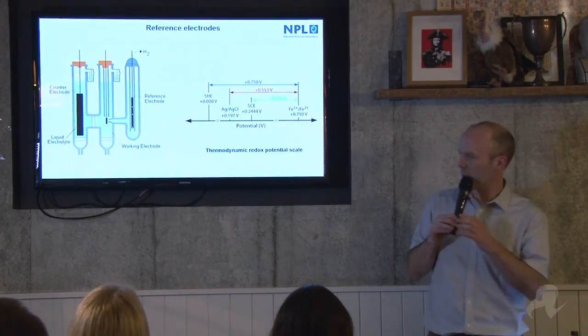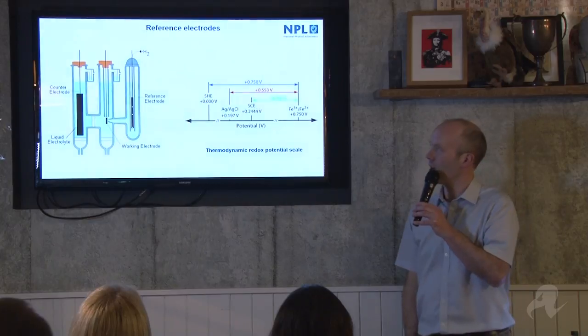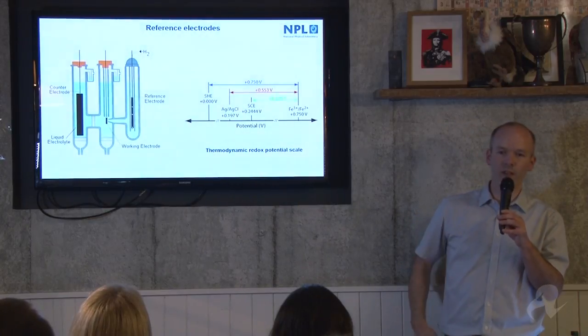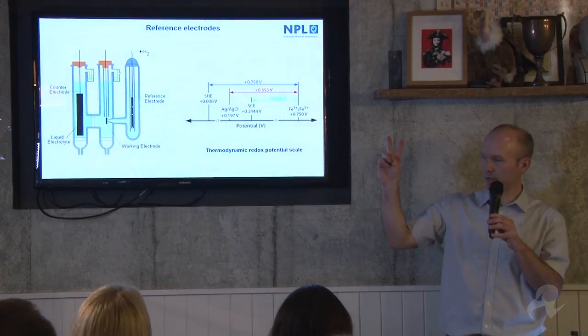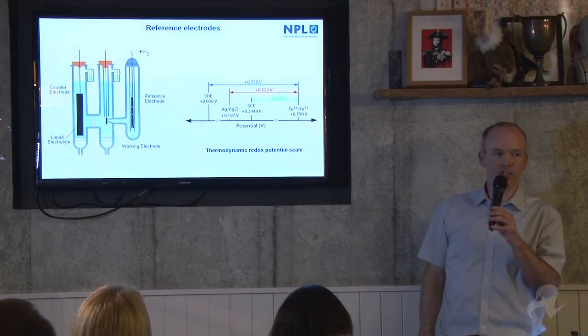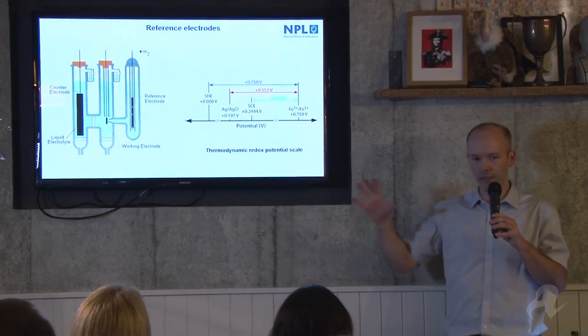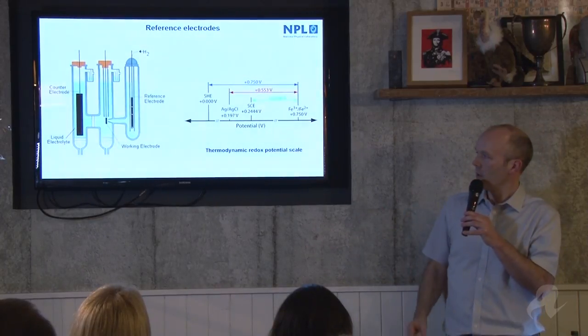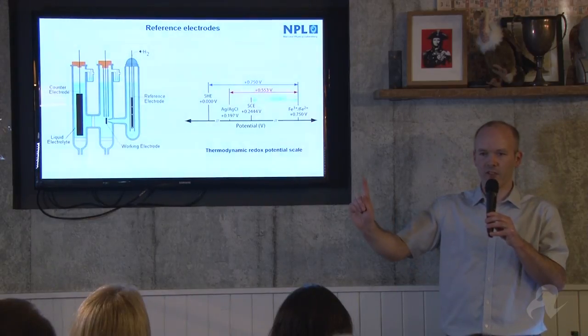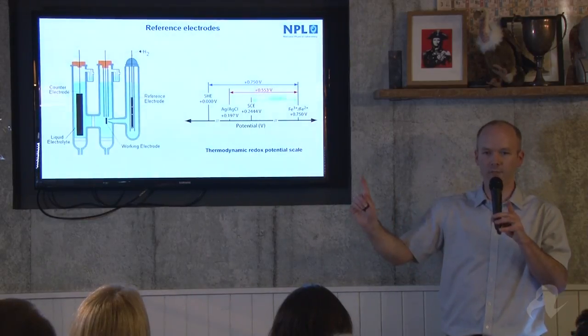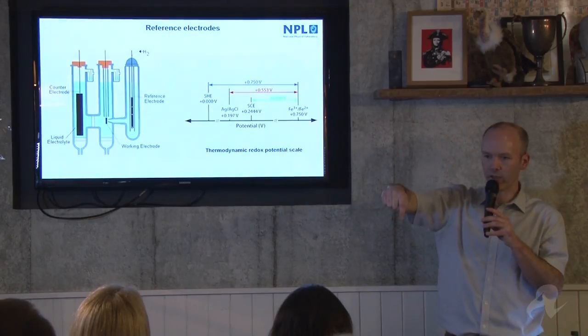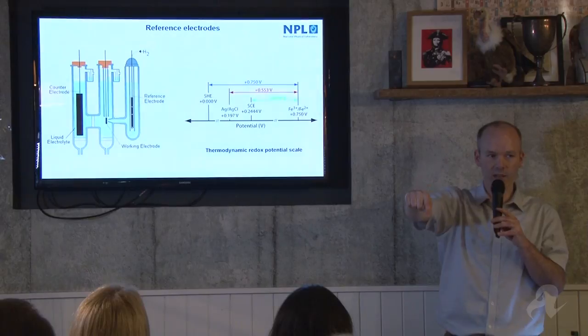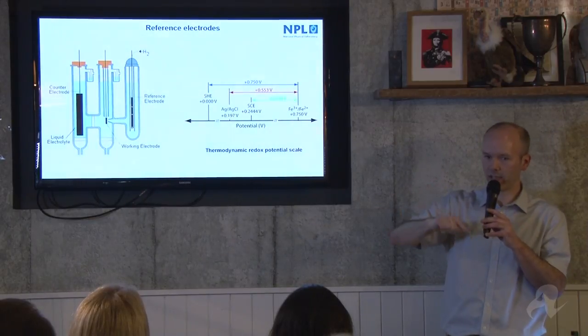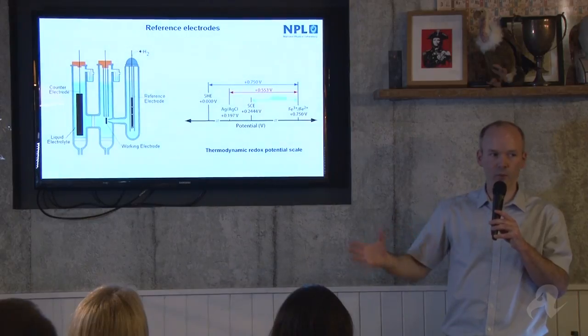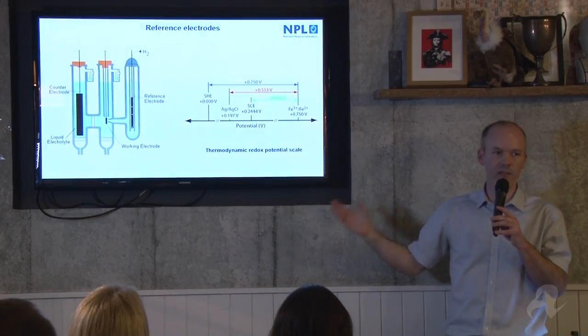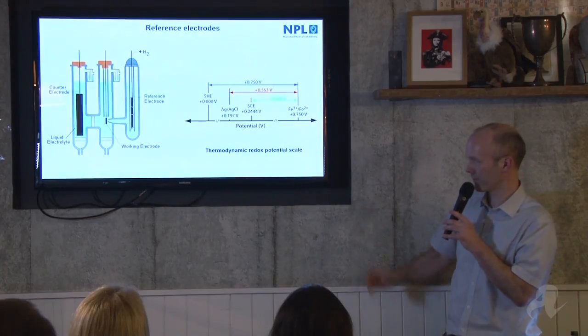So I'm going to talk a little bit about reference electrodes. Reference electrodes are the standard laboratory technique when you have an electrochemical cell with two electrodes in it, and the potential of that cell changes due to some process. It could be performance, it could be degradation. You don't know whether one electrode's potential is changing, or the other one, or both combined. When you put a third electrode in there and you measure the potential of each electrode against that third reference electrode, then you can identify what's happening at each electrode. And that's very important in electrochemical systems such as batteries, fuel cells, and electrolyzers, as you'll see.